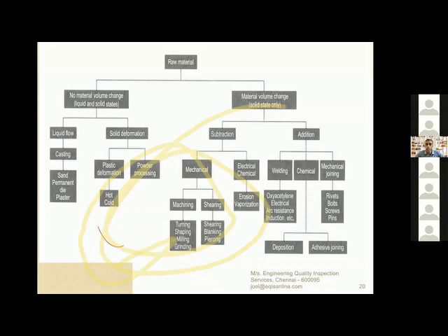So when I'm trying to join two metals, I'm trying to bring in two metals that are completely homogeneous separately. And when I'm trying to join them together, then I'm trying to change the volume of the material, which has its own kind of defects that are induced during that production process. So basically, whenever there is a change in volume, the chance of getting a defect is higher compared with the casting defect. But again, casting is an inherent defect. We call it a dormant defect, for example.